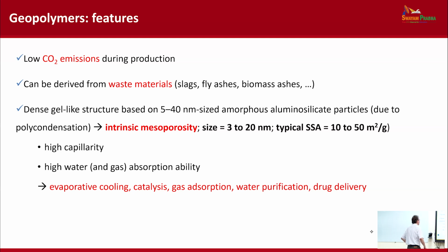The fact that the porosity is meso means that the typical specific surface area values are not very high, but we can control that and increase the specific surface area up to almost 200 square meters per gram.